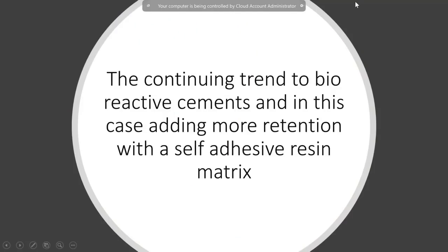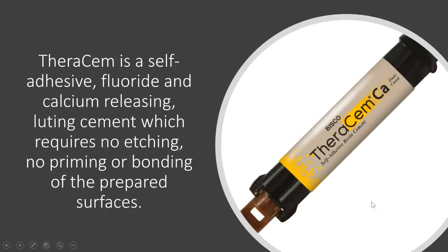So the continuing trend is to bioreactive cements. Now, what they call bioactivity, well, in my eyes, it's bioactivity when you really can reseal margins. But if we can start to go in this direction, amazing. So what we're adding now is a self-adhesive resin with calcium silicate. So Theracem is a self-adhesive, fluoride and calcium releasing luting cement.